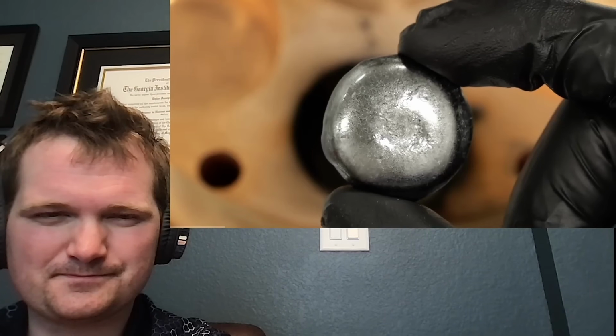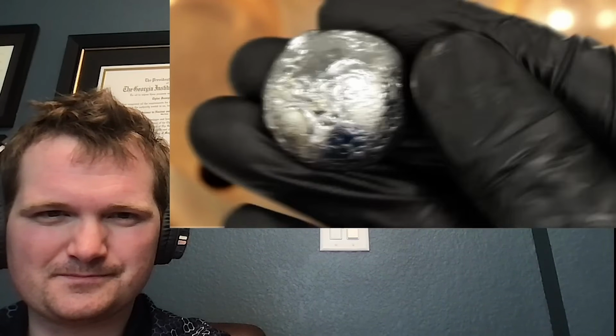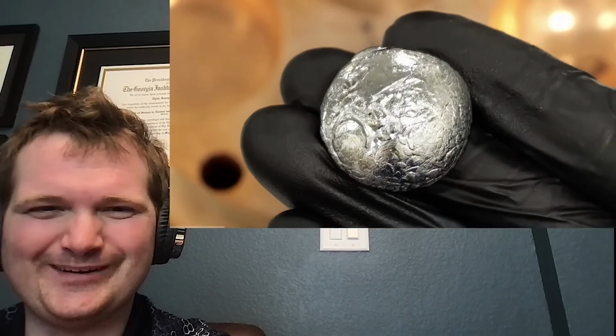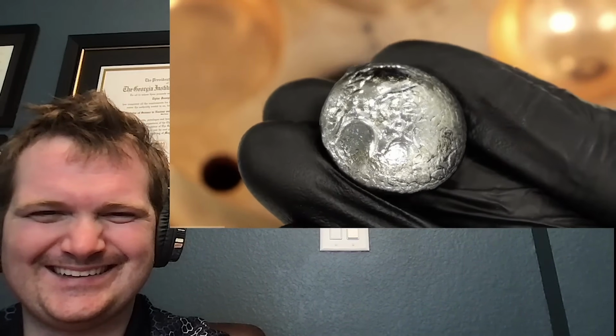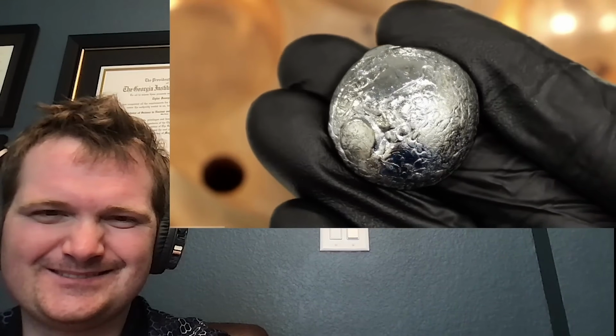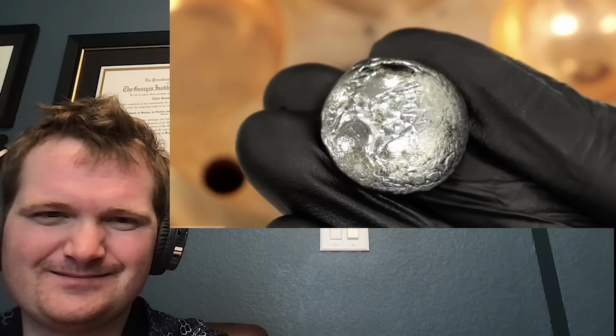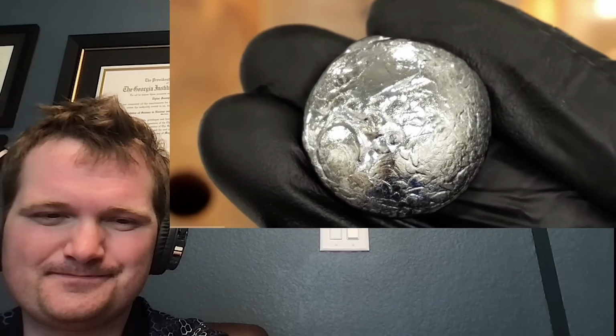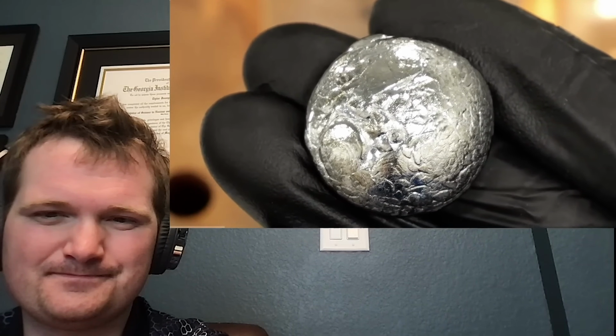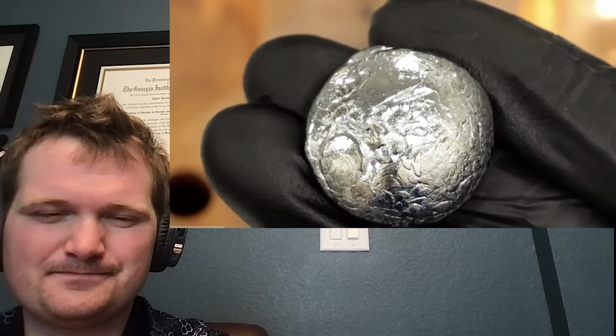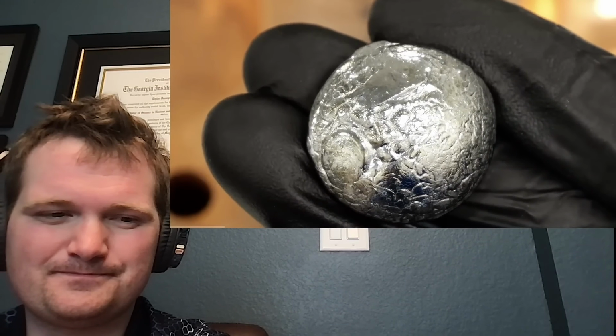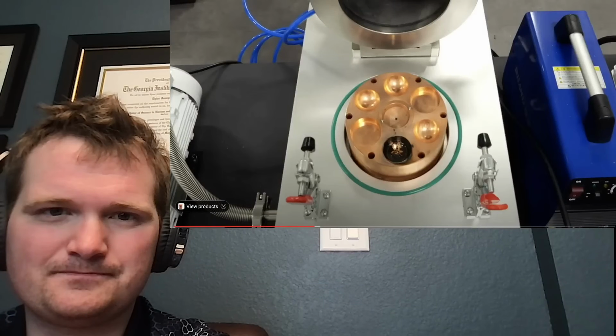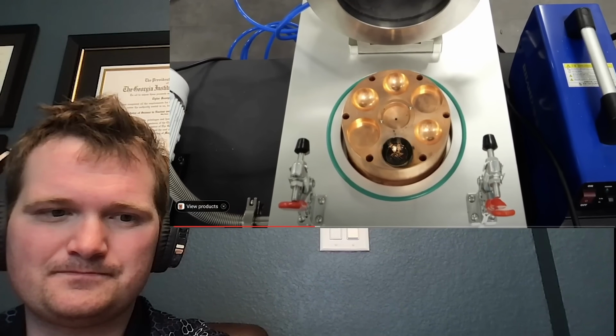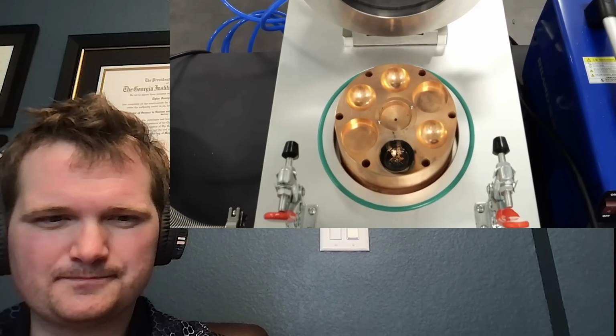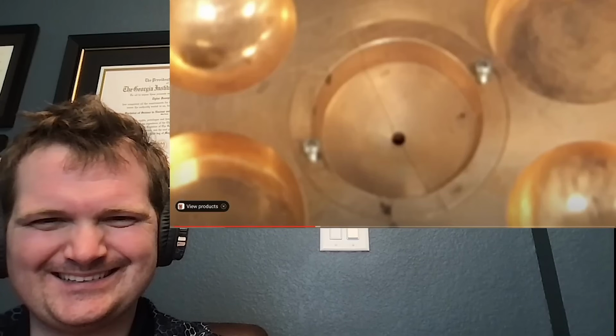I then took a closer look at it, and when I flipped it over, I noticed that the bottom side wasn't properly melted. I really thought that I had avoided this by absolutely blasting it, but clearly the cold copper really did its job, and the stuff at the bottom would probably always struggle to melt. But moving on, the machine clearly worked, and now, the only other thing that I had to do before working with the scary beryllium was test the mold.